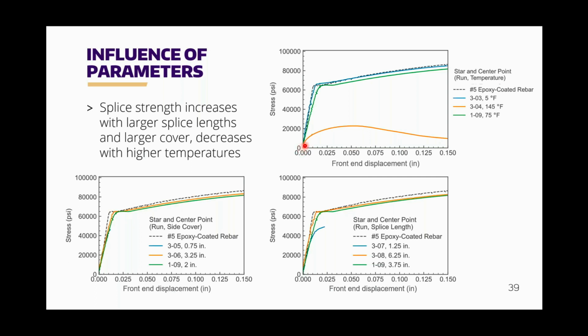Whereas at 145 degrees, you're seeing quite a bit of slip in the test specimen, and you see pullout occurring in that case. The last one is looking at splice length. Again, we have 3 different values here. We have the extreme ends of our design space, so a very short splice length of 1.25 inches, the blue curve here, and that is showing you that we have a pull-out failure at a lower than the yield stress. And then we have the other end where we have a long splice, and you can see that also tracks very nicely with the stress strain curve for just the rebar, the reference curve.